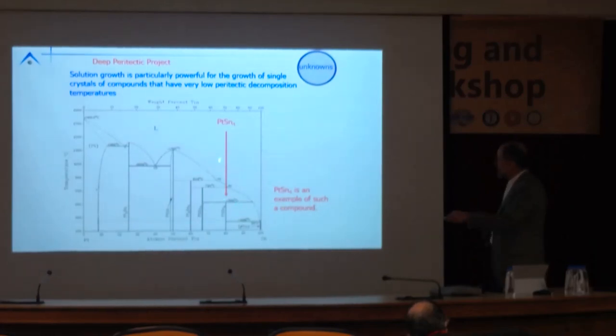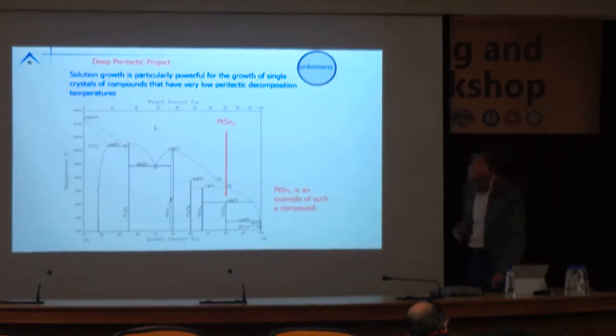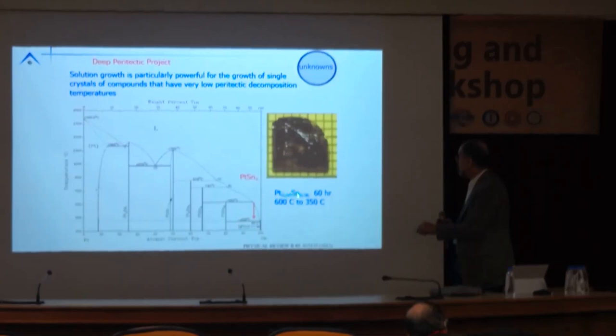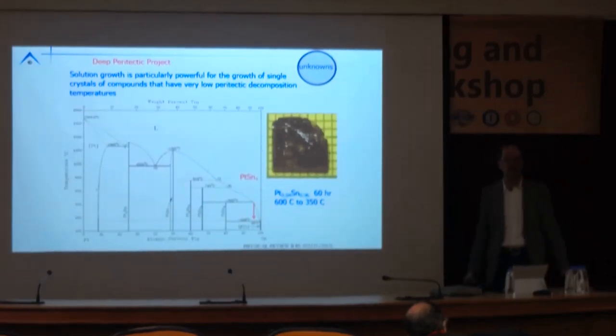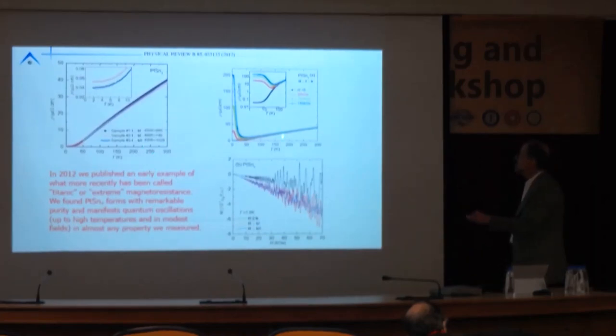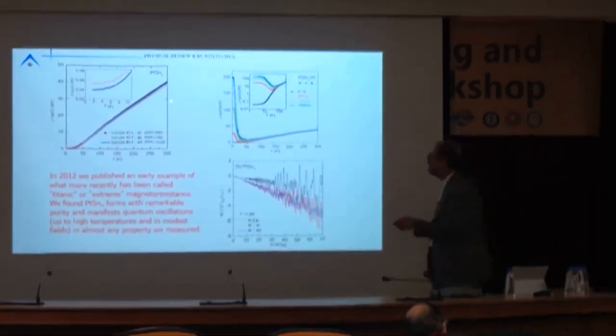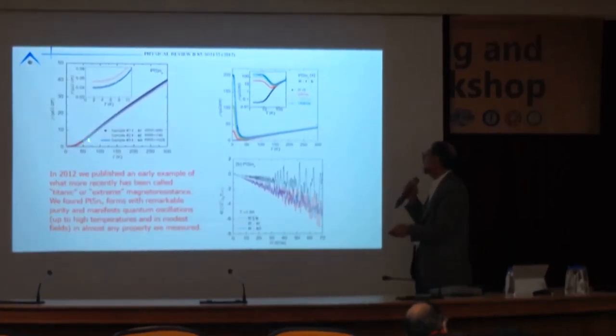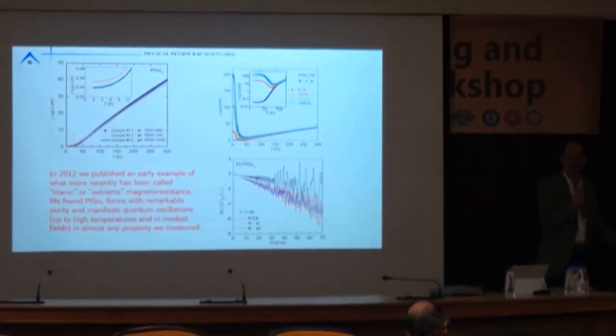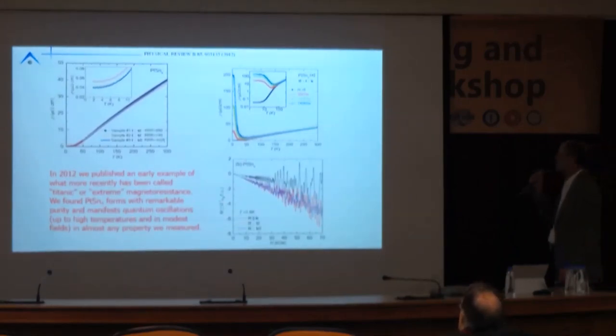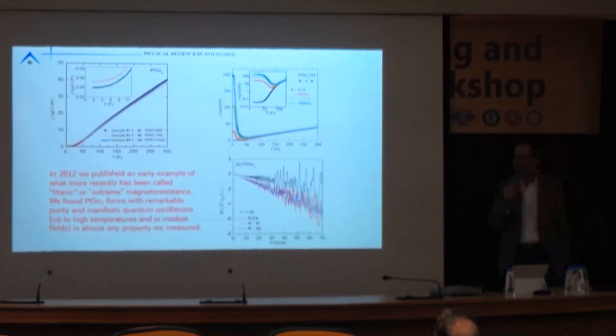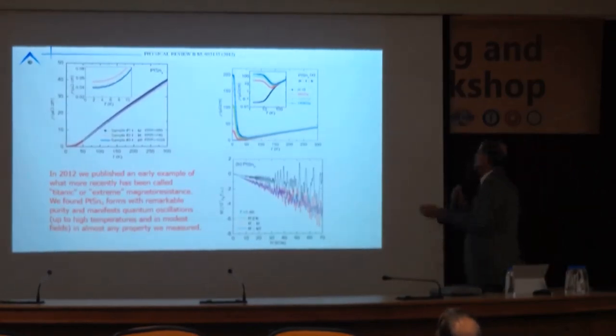This is a material that is somewhat deep in its peritectic temperature. And you can beautifully grow crystals of it by taking 4% platinum, 96% tin, cooling down from 600 to 350, and you get beautiful single crystals within 60 hours. So over a weekend, you get nice samples. Lovely. These are beautiful samples for metal physics. You have residual resistivity ratios in excess of 1,000. Now, having said that, if you measure the resistivity in a field, you can see that at 14 Tesla, this screams up. You have huge magnetoresistance, about 500,000% magnetoresistance. This is sort of the original extreme or titanic magnetoresistance. We found quantum oscillations in anything we care to measure. So this was interesting.